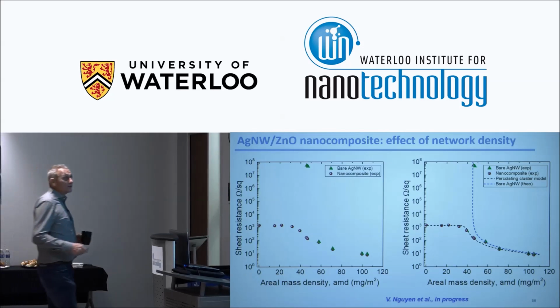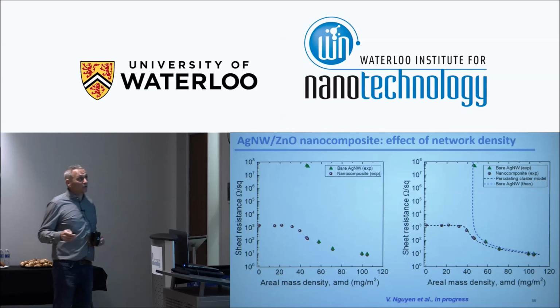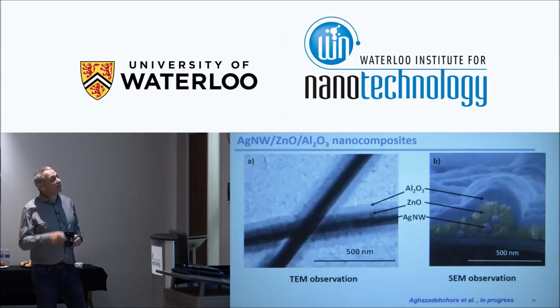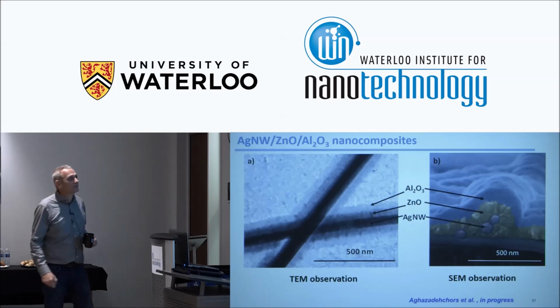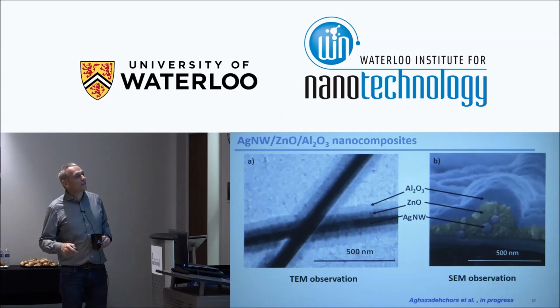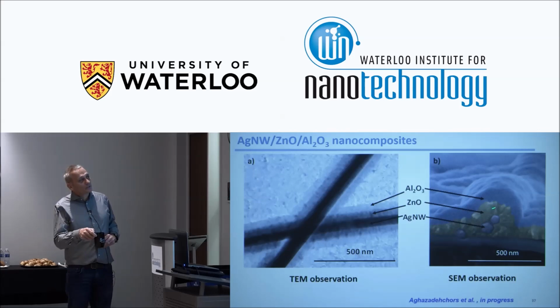The point is that we have seen before that the transparency is lower, so maybe there is another interesting point: at the top of the zinc oxide, again, still by using spatial atomic layer deposition, we can deposit some alumina layer, and we can see a TEM picture. We have the silver nanowires in black, zinc oxide and alumina here. This one is a bit thick because we wanted to observe that with a TEM or with a SEM, but it could be thinner. And again, with a cross-section with the SEM, you have the silver nanowires here with a 5-fold symmetry. This is the zinc oxide and alumina around.